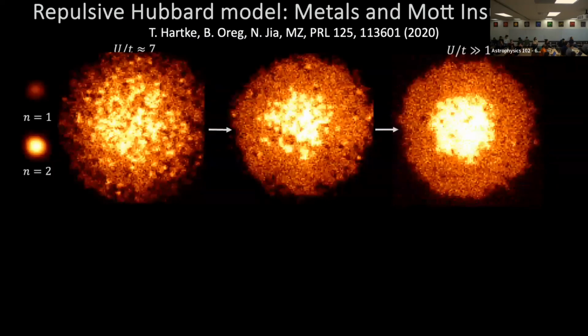Here comes the repulsive Hubbard model, first things first, which is happening in a trap. So you have an overall trap switched on. That means the high density regimes are, of course, in the center. That means you get 2 atoms per site in the center. You cannot have 3 atoms per site because you have only 2 spin states, and we are thinking about the single band Hubbard model. We gap out the other bands of the optical lattice.